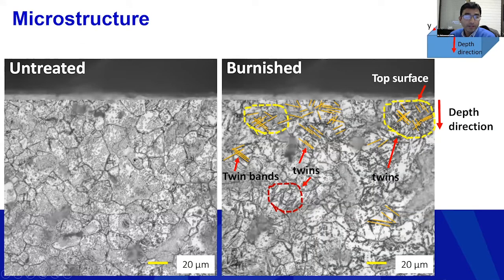To see what happened to the microstructure of this material, this is the untreated microstructure. We can see that the grain of the microstructure is quite large, quite uniform, with a quite large grain distribution. However, when we apply the burnishing, we can see a bit of change in the microstructure. We don't see much grain refinement, but you can see twins at the top layer. Twins and twin bands are generated from the top surface, and as we go down, we see more of the bulk distribution of the microstructure. So there is not much change of the grain.